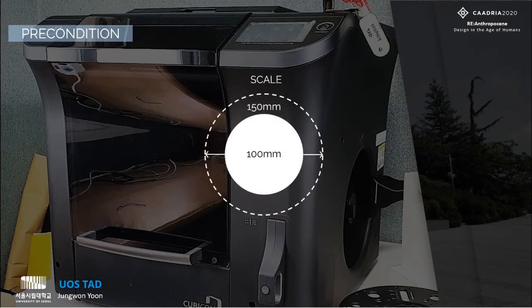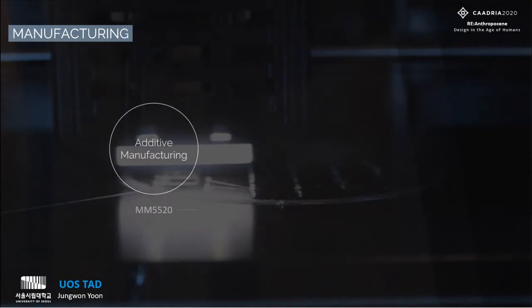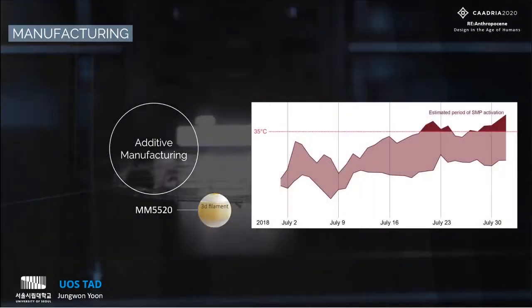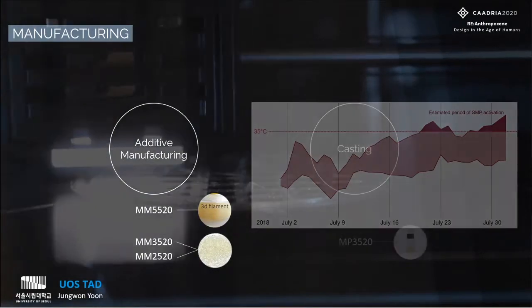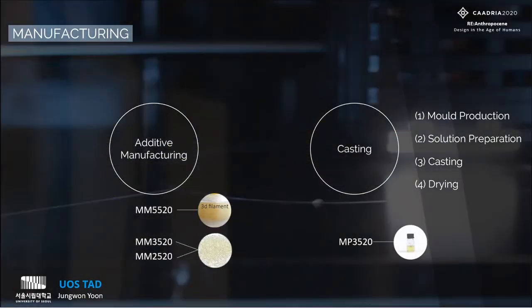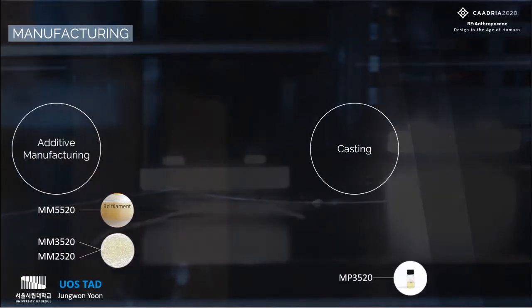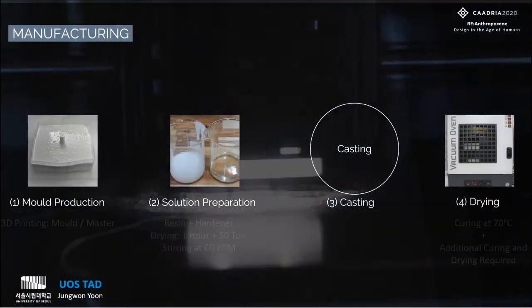In the early stage of additive manufacturing, the commercially available filament MM5520 was used. To achieve more responsive SMP components in real temperature conditions, MM3520 and MM2520 were tested for 3D printing after making custom filaments. Additionally, to verify the efficiency of 3D printing by comparing different manufacturing methods for SMP, casting was also experimented. Casting proceeds in 4 steps. First, mold production; second, solution preparation; third, casting; and lastly, drying and curing.